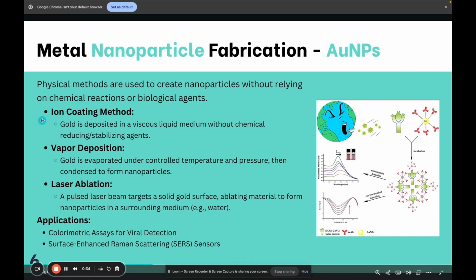So the first method, commonly used, is the ion coating method. In the ion coating method, gold is first deposited in a viscous liquid medium without chemical reducing agents. This produces uniform nanoparticles with narrow size distributions. It also offers high precision in controlling particle size and morphology. Then comes the vapor deposition method. Gold is evaporated under controlled temperature and pressure, then condensed to form nanoparticles. This allows fine control over shape, size, and film thickness, and